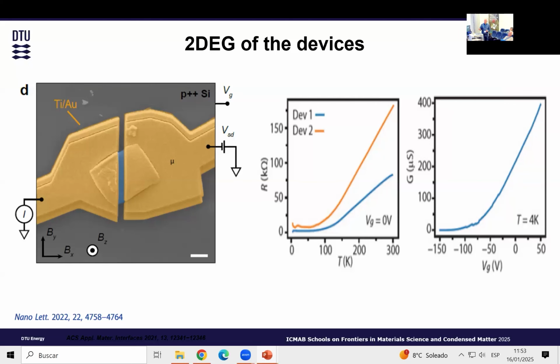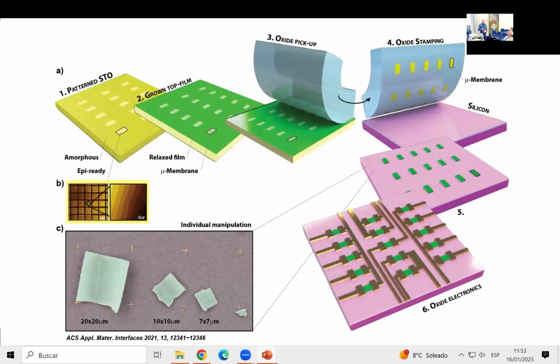And then what can we use it for? This is a little bit a vision and a little bit experiment. What you see below is an experiment that we did. We also tried to trench the silicon here. When we trench the silicon to a certain size, we can basically predetermine the size of the membrane. Doing that, we can pattern the STO. And now it's a vision. We are currently trying to do it, but this is just for you.